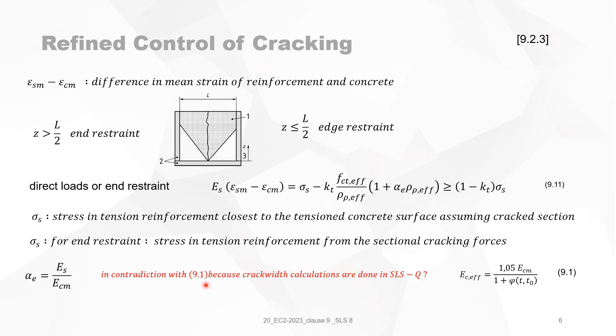Alpha E is the ratio of the modulus of elasticity of steel to the concrete. The mean modulus of elasticity of concrete is stated here. This formula is actually in contradiction with formula 9.1, because crack width calculations are done in the serviceability limit state — meaning long-term calculations. Formula 9.1 states that the effective modulus of elasticity equals 1.05·ECM divided by (1 + φ), the creep factor. So using ECM without the creep coefficient φ violates formula 9.1.